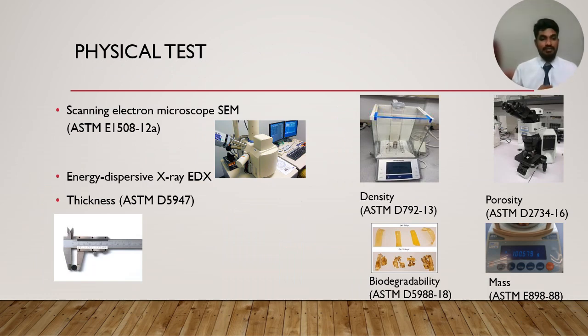So, for physical tests, there will be scanning electron microscope SEM, energy dispersive X-ray EDX, thickness, density and porosity, biodegradability, and the mass. For the SEM, the ASTM E1508-12a will be used to determine the microstructure of the sample, and EDX analysis will be conducted at the same time as the SEM test because it uses the same machine. The thickness of the sample will be measured by using a vernier caliper. The biodegradability test will be conducted by solubility according to ASTM D5988-18. The mass will be calculated before and after the biodegradation process of the thin film.